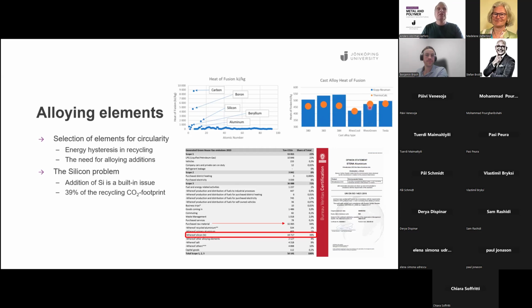And what we know is that in mega casting, there is also an alloy change. So you will not use these A380 type of materials for most of the large body in white materials, but it will be something more like the Tesla alloy with slightly lower silicon contents and a different structure, so to say. So the Tesla alloy is represented here. It also has a slightly lower energy content, but we can do better in alloy development.